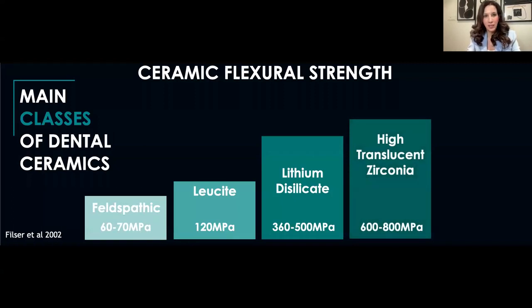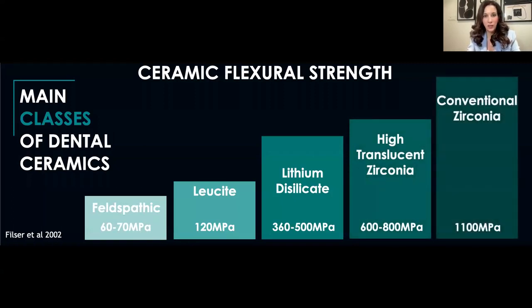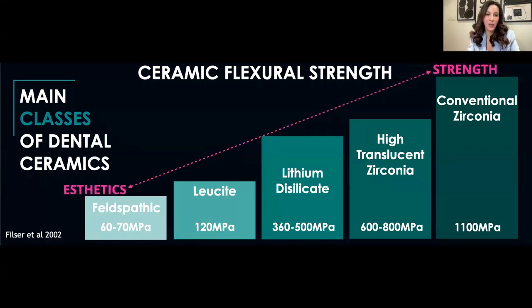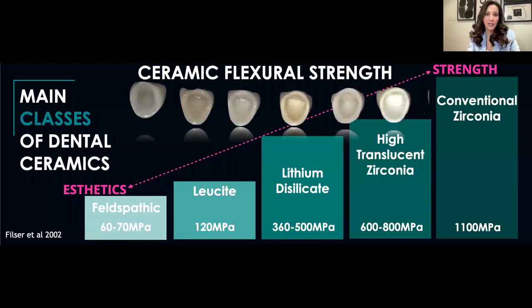And then we reach our zirconias. We have our conventional zirconia, which is the strongest material at over 1100 megapascals of strength, and the high translucent zirconia, which is 600 to 800 megapascals. So if you look at this graph, you can appreciate that the weakest material, the feldspathic, is in fact the most aesthetic, and conversely, the strongest, the conventional zirconia, was historically considered the least aesthetic. But what I'm going to do throughout this presentation is show you how the materials have advanced, what materials we have available today, and what I use most in my clinical practice.